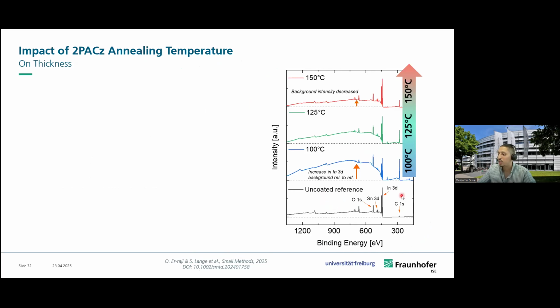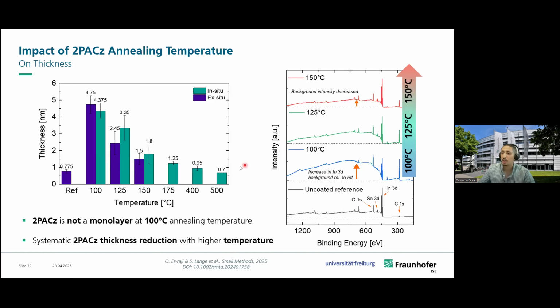So by doing this variation, here you can see an uncoated reference that doesn't have any SAM. Here we have SAM annealed at different temperatures. You can clearly see how the background really changes with annealing temperature. And by extracting a value for thickness, you can see the in situ annealing series, but also ex situ in order to confirm the trend. You can see that at the standard temperature that is used in literature, which is 100 degrees, we don't have a monolayer, because a monolayer of 2PACz would be around 1 nanometer, but here we have around 4 nanometers, so it's not present as a monolayer.